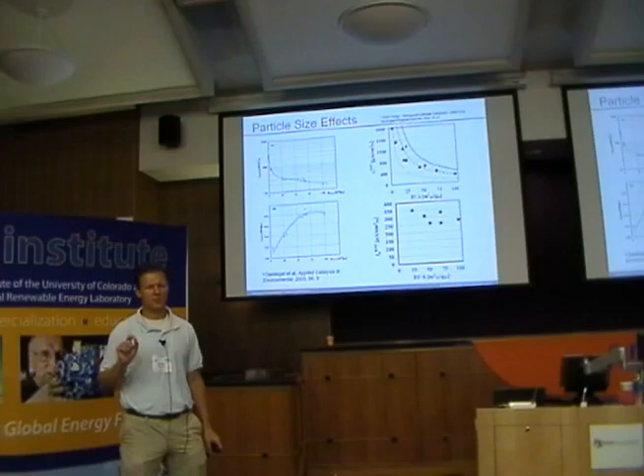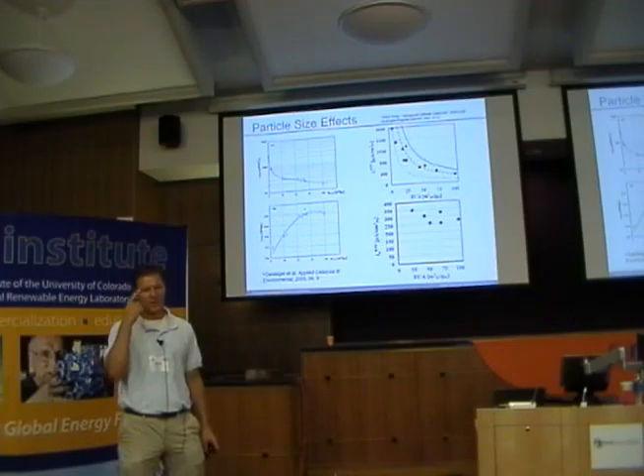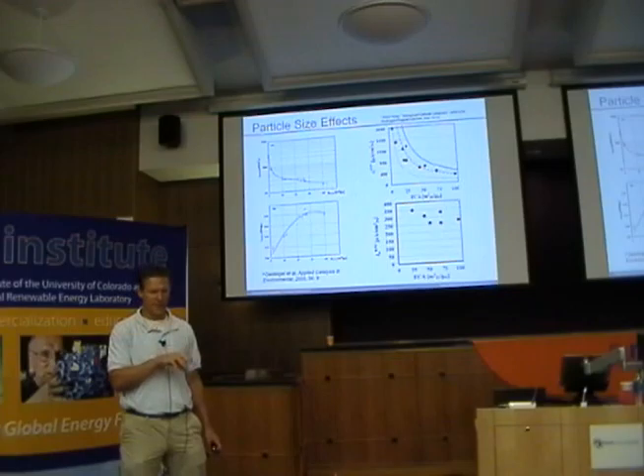When it comes to different materials or different reactions, I'm only going to be really good at the oxygen-hydrogen ones, and methanol or other types of things. So you'll find that people will put ruthenium in with platinum so it will do methanol, and that's based on a bifunctional mechanism. When it comes to oxygen, what they've done is they looked at all the metals, figured out that platinum was the only one that was stable in acid, and then figured out how to alloy it to improve it as well. And so they're usually really good with the models in terms of understanding which metals are good for which reaction pathways.